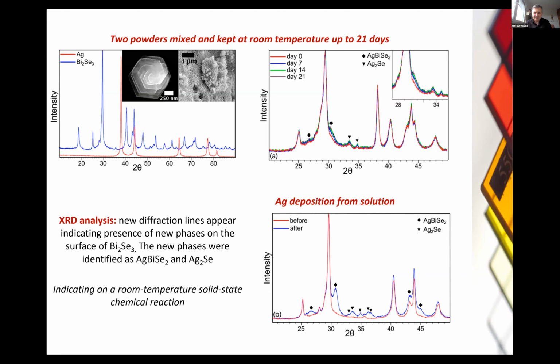To enhance this interaction, in the next experiment, we soaked bismuth selenide nanoparticles in a solution of silver nitrate, with silver ions in the solution. And this resulted in a much more intensive reaction, and the peaks became even bigger, and we were actually able to identify the products.